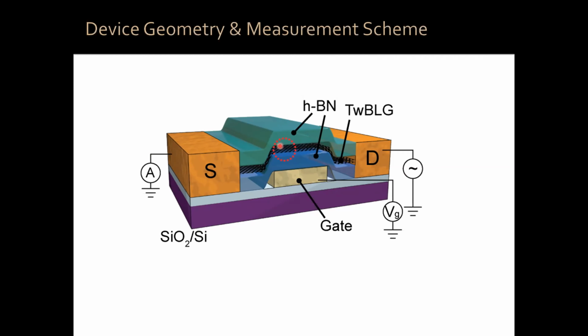And these devices are encapsulated by two crystals of hexagonal boron nitride, which is a very high quality insulator. And then they're contacted by source and drain electrodes so that we can apply a voltage and run a current through the twisted bilayer graphene system. And we also have, interestingly, a metallic electrode, which acts as a gate so that the whole geometry is that of a field effect transistor geometry. With this gate, we can change the density of electrons in the twisted bilayer graphene by applying a gate voltage, by applying an electric field.